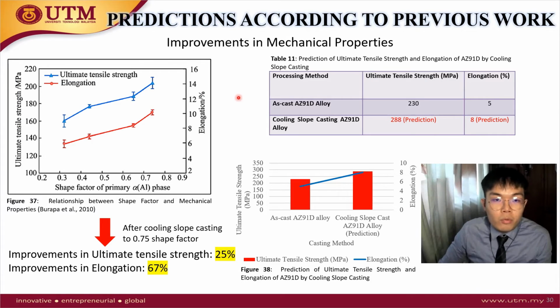And we move on to the improvements in mechanical properties. Figure 37 shows the relationship between shape factor and mechanical properties. As you can see, as the shape factor approaches 1, the ultimate tensile strength and elongation are getting higher. So you can see after cooling slope casting to 0.75 shape factor, the improvement in ultimate tensile strength has grown 25%, and the improvement in elongation is 67%.